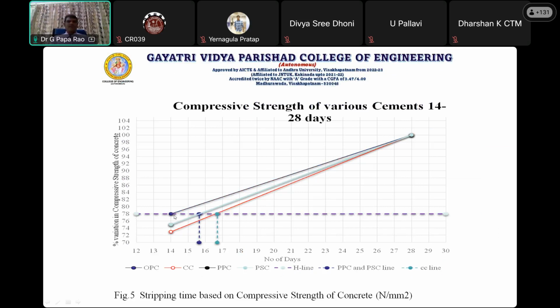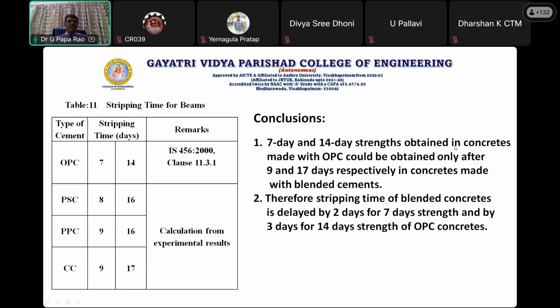Here we have our OPC getting 78% of its 28-day strength at 14 days. Therefore, again we have taken 14 days at 78% as the base. Again we have compared at what ages, at what duration our other remaining cements get the same percentage, 78%. If you observe, our other cements get the same strength at 16 days, 17 days, likewise. So again, we have tabulated the same.